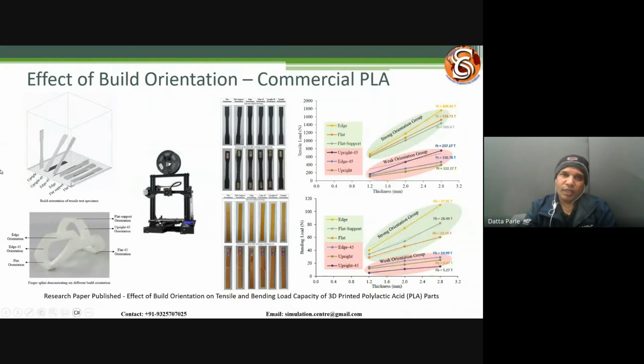One is a strong orientation group, that's flat. So this is the one. And then edge, this is an edge when you print on the edge. And then flat support, they become strong. These parts definitely were always strong, and that's what my experience was expecting. And these upright 45 and edge 45 become weak in both cases, whether it is bending strength or tensile load. So in both cases, we came across clear groups and the orientations are the same.